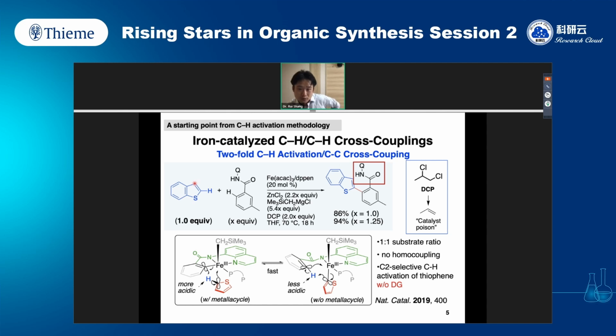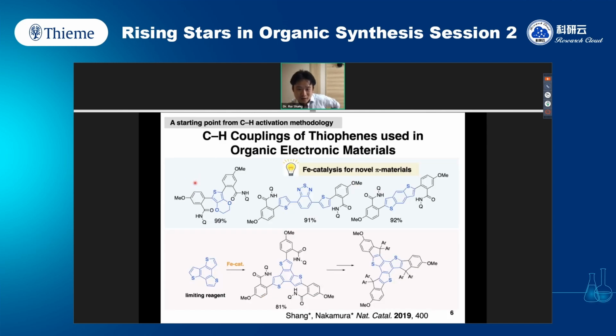Interestingly, this is different from reactions using other late transition metals. We work only with iron. The iron-catalyzed system is very good for conjugated, especially electron-rich conjugated thiophenes as substrates. This makes me feel very interested, and it gives me a hint for polymerization. It means that more conjugated oligomers will work better, or at least will not decrease their reactivity towards the catalyst. So we can make monomers to oligomers, and oligomers even to polymers. Of course, the problem is that this bidentate directing group is not something desirable in polymer synthesis. This is the directing group.